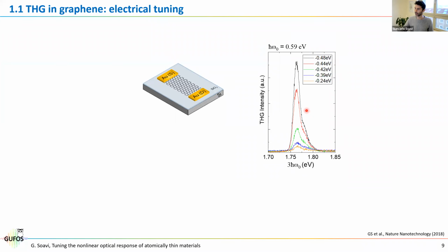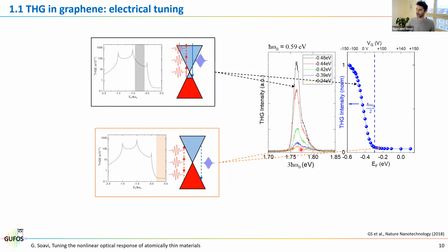And then by doing that, you can immediately appreciate the fact that the third harmonic can be heavily tuned by changing the Fermi energy. But in order to make it a bit more clear, I will do the following. I take each of these curves, take the integral, so the total number of photons, and then plot it on this graph on the right. And as you see here, when the Fermi energy is close to 0, so we are at the Dirac point, then the efficiency of the third harmonic is flat and relatively low. But as soon as we hit this special point, so the Fermi energy equal to h bar omega 0 divided by 2, the one photon resonant condition, then we have this very rapid increase in the third harmonic efficiency.